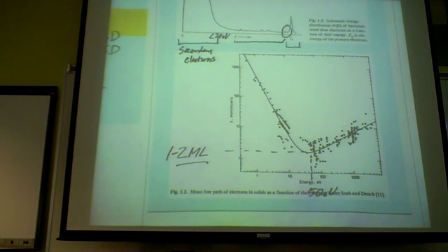And why you need to know this is because if you send an electron beam of about 50 or 70 electron volt, you would get the most surface sensitivity, because any electron that comes out will be coming out from one to two monolayers deep from your surface, right?